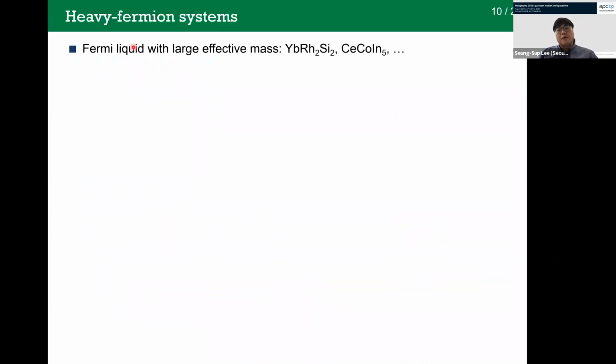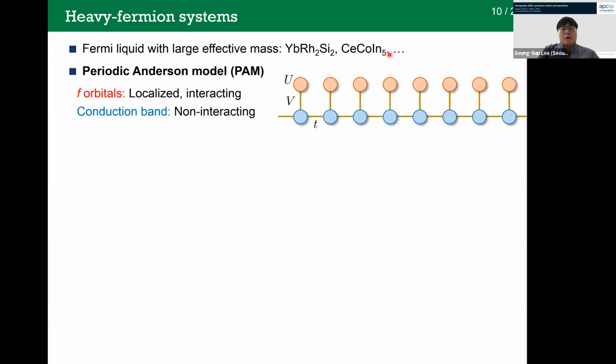So heavy fermion systems are in the Fermi liquid region, but with a very large effective mass. Their effective mass can be hundreds or thousands of times larger than the bare electron mass. The examples are ytterbium rhodium disilicide or cerium cobalt indium and many others. As a theorist, we wanted to start from the simplified, basic model that can capture the key ingredients of these materials. So we started from the periodic Anderson model, which has two orbitals at each lattice site. One orbital is the f orbital, which is localized and interacting, and the other one is non-interacting, forming a conduction band. These two orbitals are coupled to each other via this hopping amplitude V, and we'll use this V as a driving parameter for making a quantum phase transition.